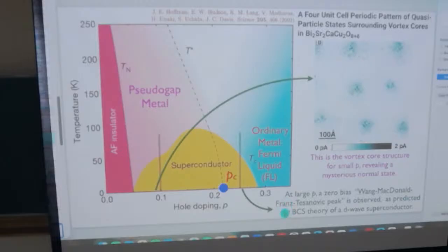The BCS theory predicts a large zero bias peak, not a suppression, but a peak. In the bulk of the sample, you have a d-wave superconductor, so there's a gap. When you get the vortex core, because it's gapless along certain directions, you get this peak. In an s-wave superconductor, you get these Caroli-de Gennes-Matricon states, and in a p plus ip superconductor, you get Majorana fermions.